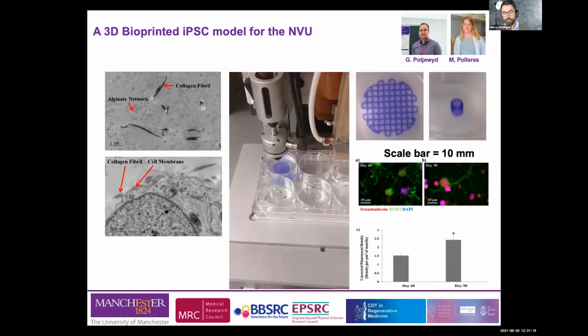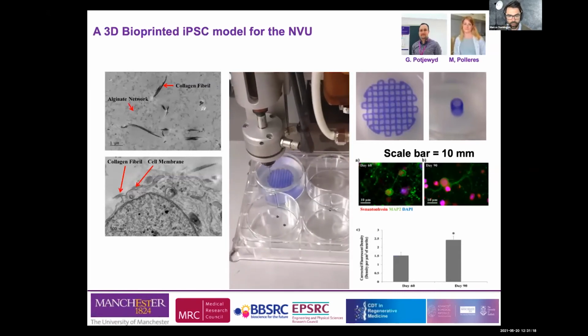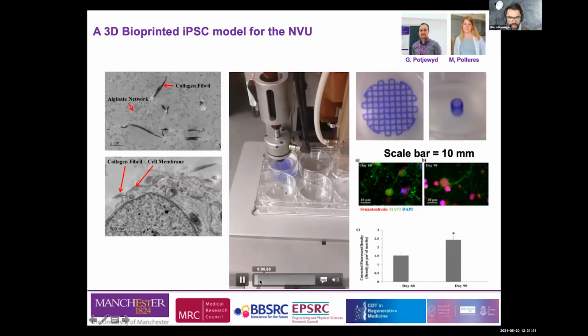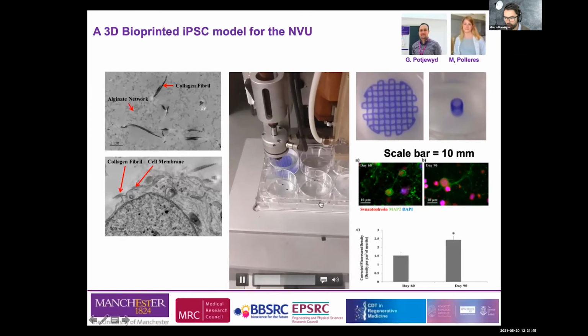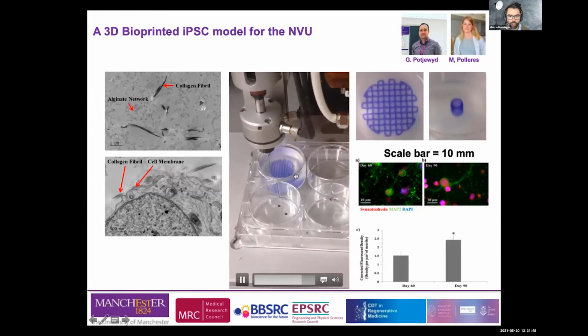Our work initially was very much focused on developing cell-laden hydrogels for the in vitro culture of functional neurons. So we started working with alginates and collagen. We're able to tune the mechanical properties and the rheological properties of the system to allow for the encapsulation of the iPSC cells, and also to allow us to actually print this in a fully automated manner. And this is what you can see here. These are directly printed into the tissue culture plates. They maintain their shape and dimensions. And after printing them, we were able to validate the process by evaluating the function of the neurons. So these are functional neurons, as you can see here, fully mature. And this was the initial work developed by Sam.